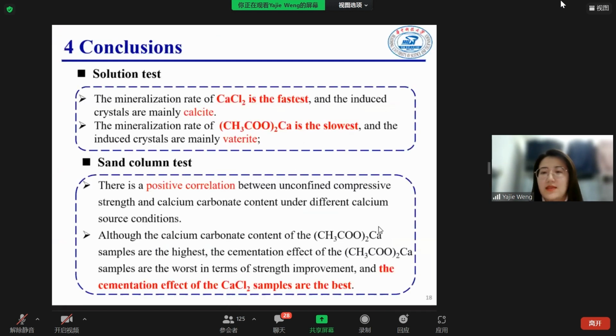Finally, we can see from this research that in the solution test, the mineralization rate of calcium chloride is the fastest, and the induced crystals are mainly calcite. Calcium acetate is the slowest, and the induced crystals are mainly vaterite.